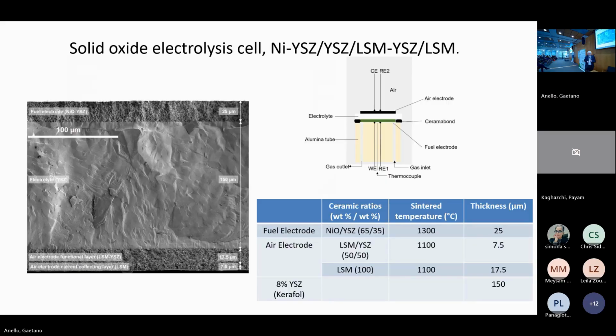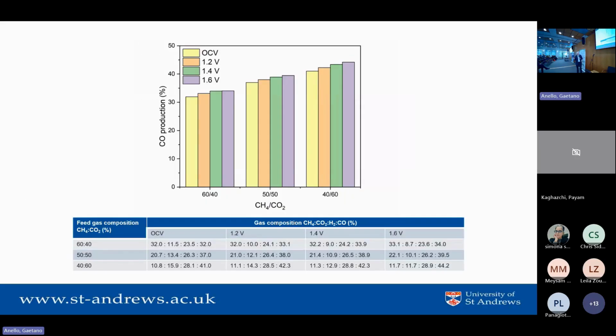So when we fed CO2 and methane into a nickel YSZ fuel cell, with a conventional electrode and a lanthanum strontium manganese air electrode, the CO2 and methane mix into that. And you can see, first of all, that the carbon monoxide production increases as we apply current and increase the voltage: more current, more CO conversion. So the gas composition changes.